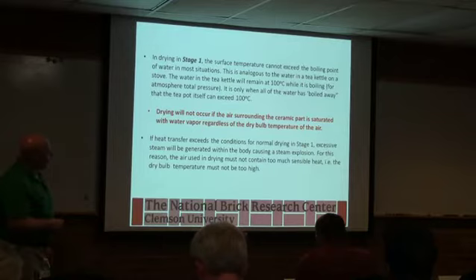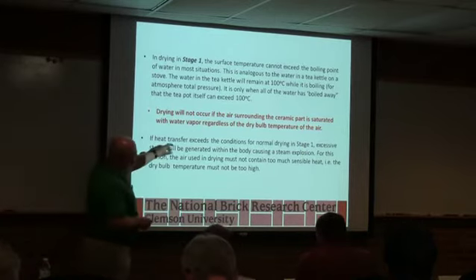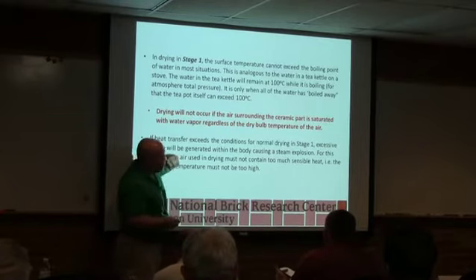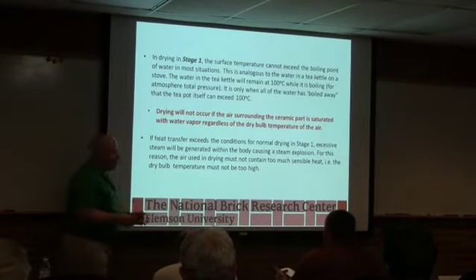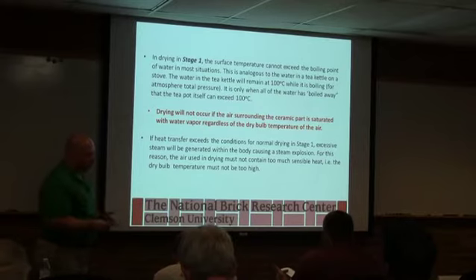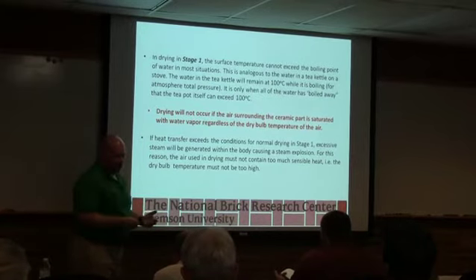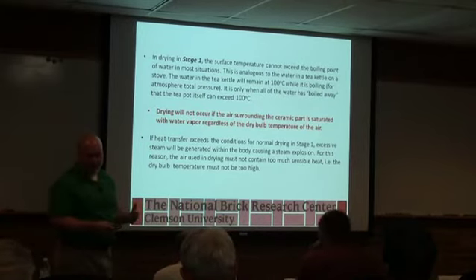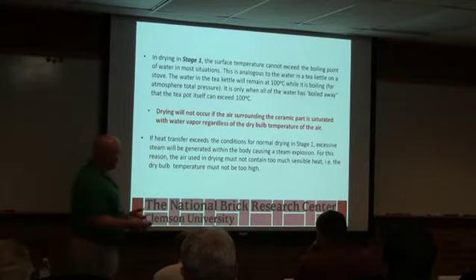So in stage 1, this is basically my thermocouple trick. The temperature of the surface won't exceed 100 degrees C or 212 Fahrenheit because that's where evaporation is taking place. It's like a tea kettle. Until all the water's gone from the tea kettle, it's not going to get any hotter than that temperature, even though you keep it on the burner and you're applying energy to it.